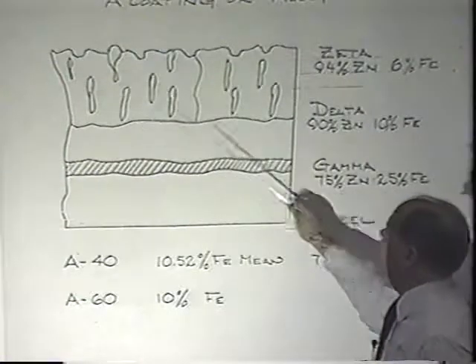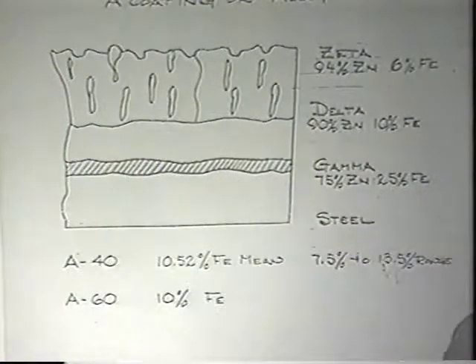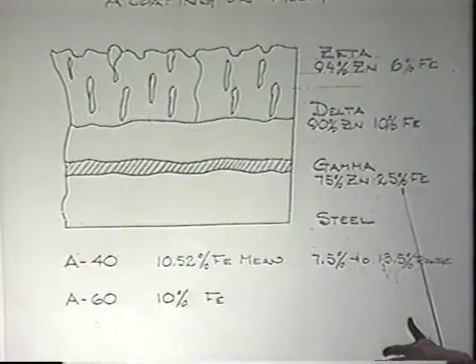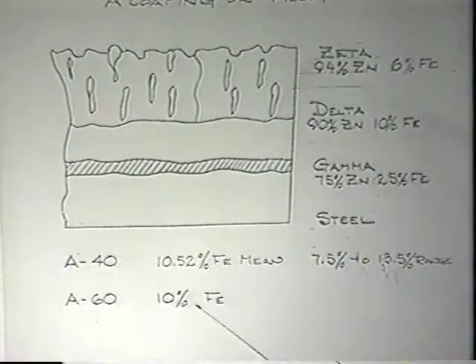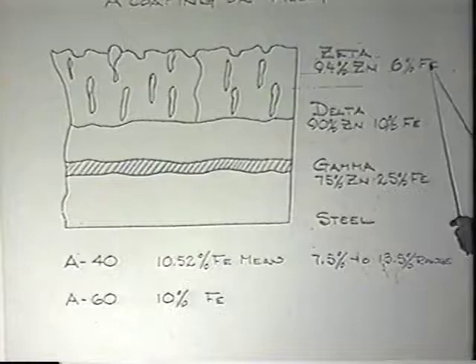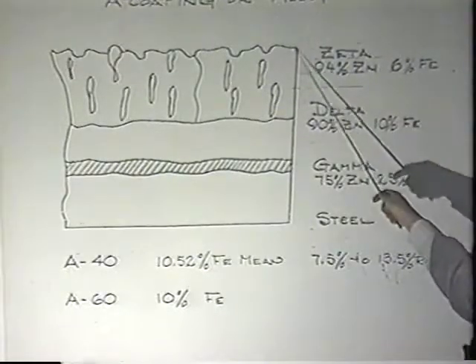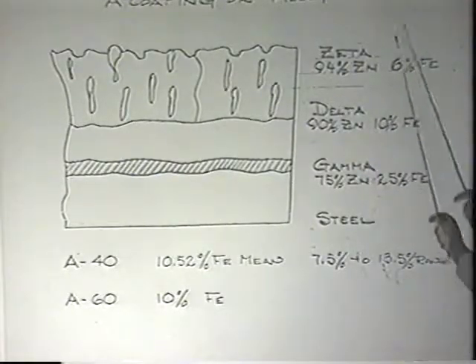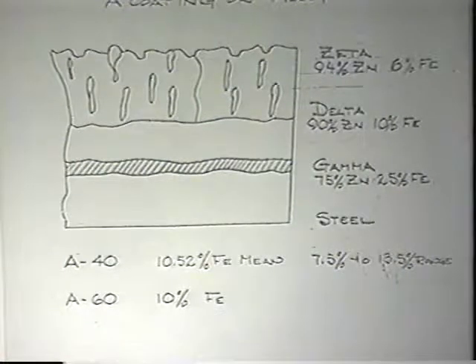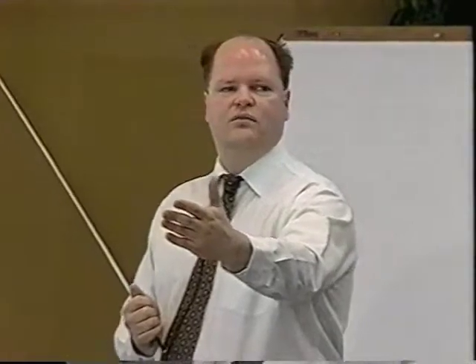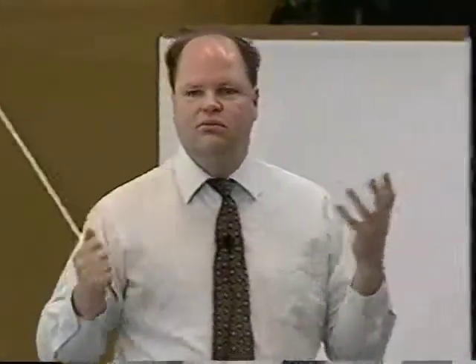And on galvanneal, you no longer have any pure zinc on the surface. It's all this zinc iron alloy, and hence it has this dull gray look to it. It looks almost like a cold rolled surface because it actually has iron on the surface. It's not just zinc there. You can see, not very much when you get right to the very top surface, but throughout it you have an average of about 10% iron in the coating. About 10% iron is enough to give it that kind of a look. And that's kind of interesting, but why would anybody want to do that? I mean, you want zinc for your corrosion protection, that should be about it.